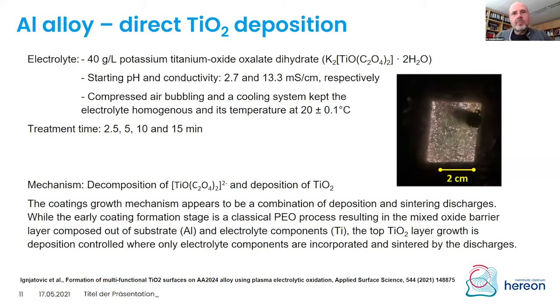So let me show you now the second example, of how we can functionalize the coatings. And this is for aluminium. Now we have the chance to work also with acidic electrolytes, which we did here. The pH was somewhere around 3. And this is the explanation why we cannot use the same approach for magnesium, because in the magnesium PEO process, we cannot start with this pH value.